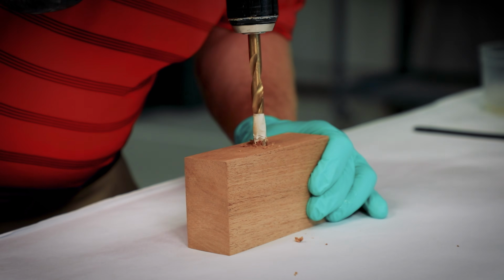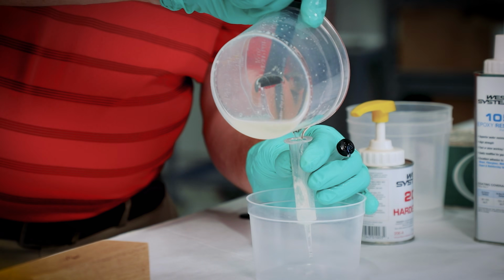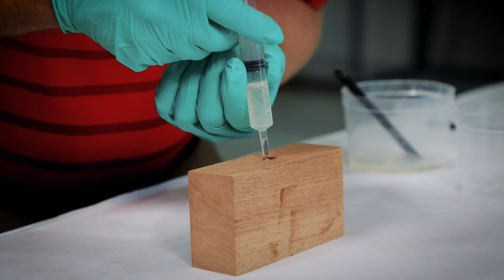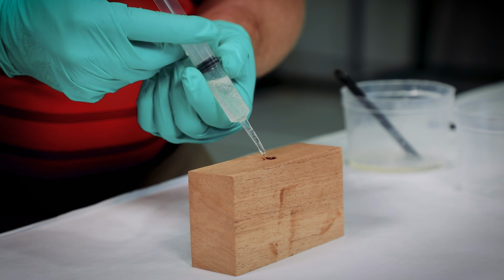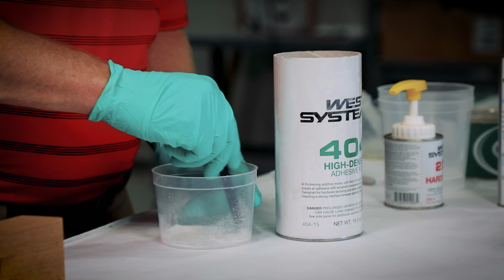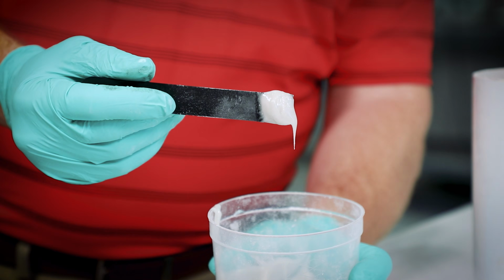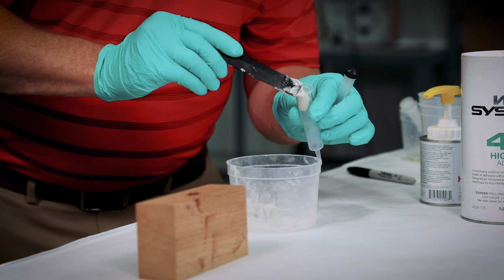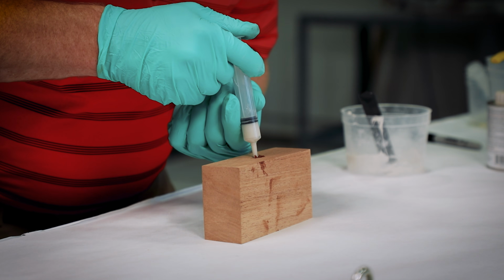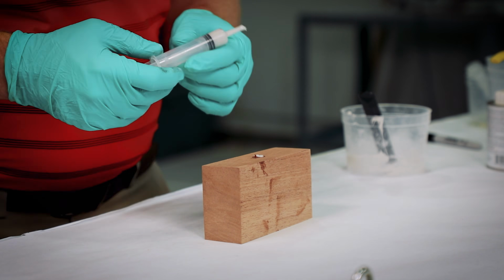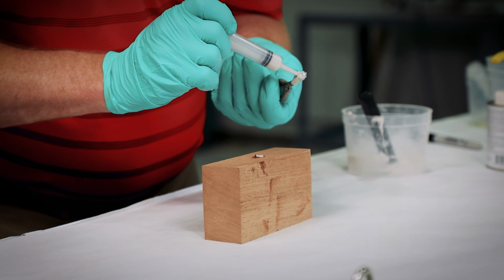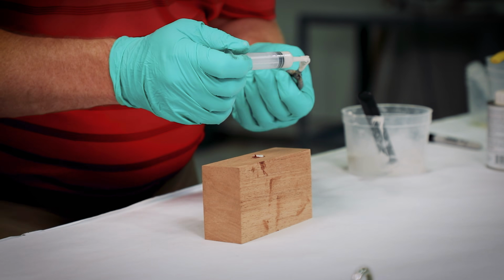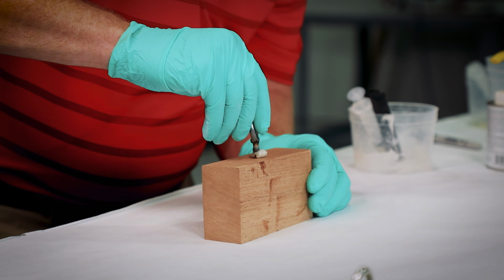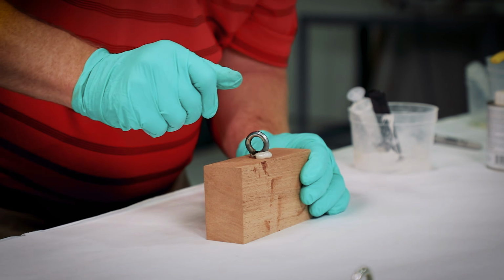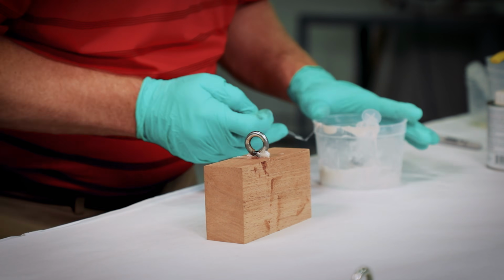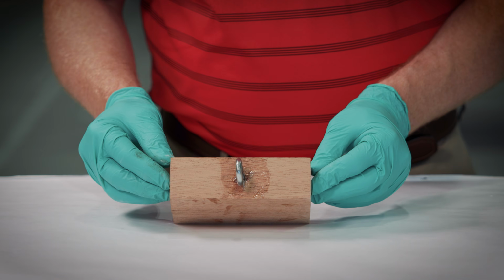Block number 4, we oversized the hole by 50% using a 3/8 inch diameter drill bit, drilling down 3/4 of an inch, leaving a 1/4 of an inch pilot hole for our fastener before we filled the area with WEST SYSTEM 105 epoxy resin and 206 flow hardener, thickened with 404 high density filler to a non-sag consistency. Another good option you could use would be 406 colloidal silica as a filler for bedding in hardware, as it is also a higher density filler.